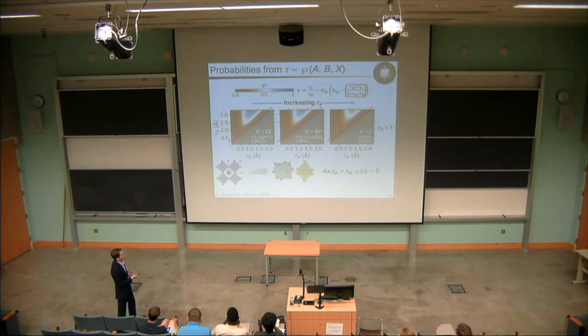And now thinking about the perovskite structure and why that particular signature might be present in the model, we know that the A site cation must be 12-fold coordinated by the anion, whereas the B site cation forms these octahedra or 6-fold coordinations. So if the radius of the A site and the radius of the B site are very similar, it's highly unlikely that the ground state configuration of this formula will include such a diverse coordination environment for the two cations. And so instead of the perovskite structure that has A coordinated by 12 and B coordinated by 6, we might find alternative structures where the coordination number is similar between these two cations.